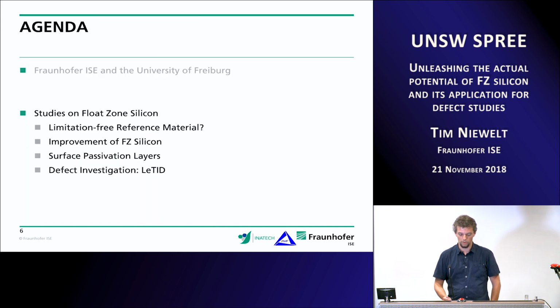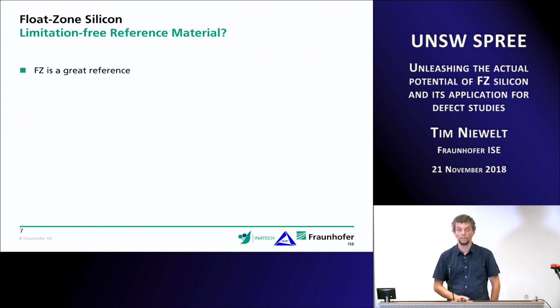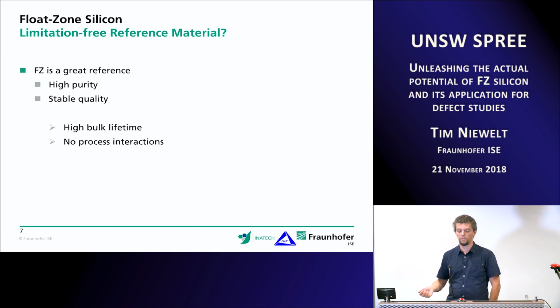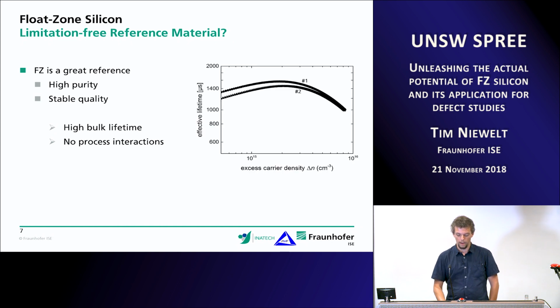So to science. I want to discuss some studies that I took part in the last 2 or 3 years on float zone silicon. So let's start with what float zone silicon is. Well, it's a great reference material. That's what a lot of you will have used it for or will use it for in the future, because it has this very high silicon material purity, and that gives us a stable quality for the material, and we wouldn't expect any process interactions when taking a float zone wafer through a high temperature process, for example.